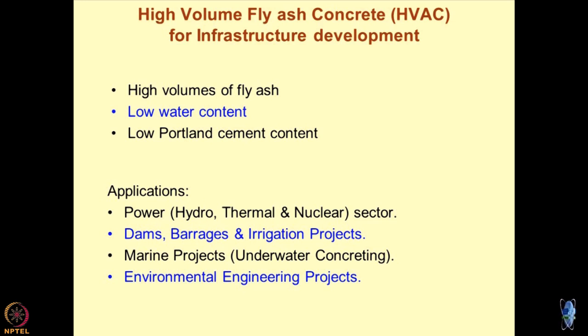These could be highly contaminated soils with very low or very high pH, high chloride contents, or high sulphate contents. At the same time, when talking about strategic structures where nuclear power is being produced — domes and shells of atomic power plants — you want extremely durable systems that are also thermally insulated. Inside, reactions are going on where temperatures might go very high, and normal concrete might crack. If normal concrete cracks, the chances are that radiation may escape into the atmosphere. So HVACs are used to create highly durable systems, and a lot of research is being done in this realm.